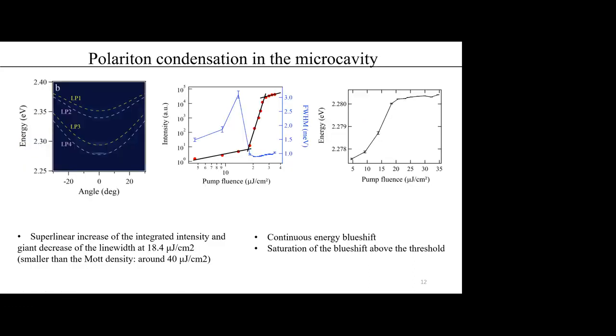Increasing the pumping power large enough, we can see the integrated intensity of the emitted light from the perovskite microcavity increases superlinearly with the pumping density, and the linewidth is reduced greatly at the threshold. During this process, we observe continuous energy blue shift of the polariton modes. We note that the polaritons condense at the ground state of the LP4 with the threshold which is smaller than the Mott density. So these experiments, we believe, clearly show that polariton condensation occurs in our perovskite microcavity.